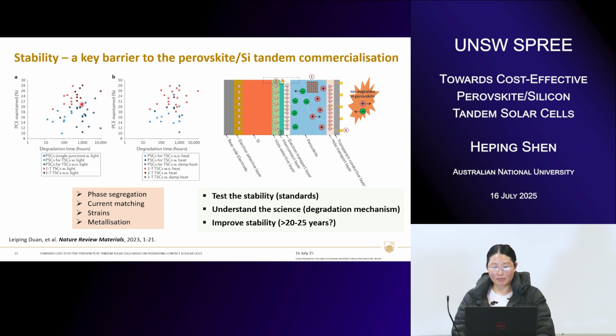We found that the stability measurements for the tandem solar cells are much shorter compared to those based on single junction. For example, for single junction, the stability tests are usually above thousands or sometimes tens of thousands of hours. But for the tandem solar cell, it's usually hundreds of hours of measurement. That can be found in the literature. That's significantly lower than the single junction, but also significantly lower than what we require for industrial stable cells. And that's one challenge.